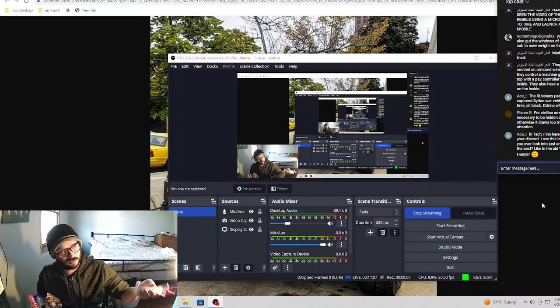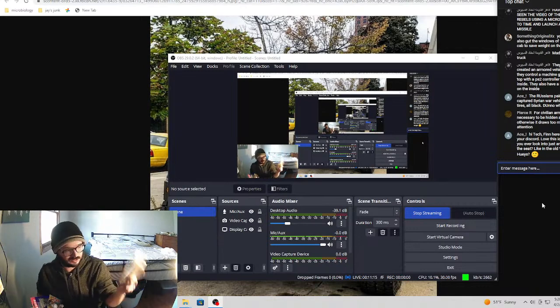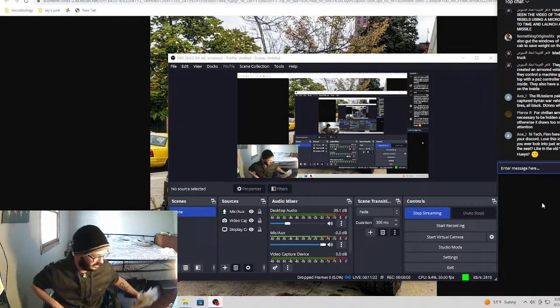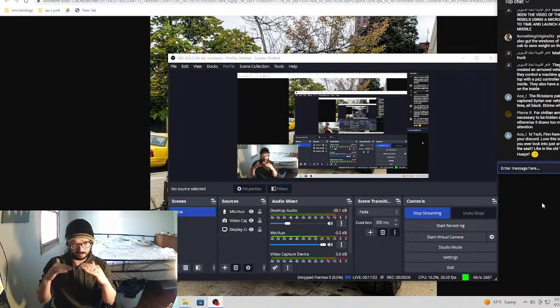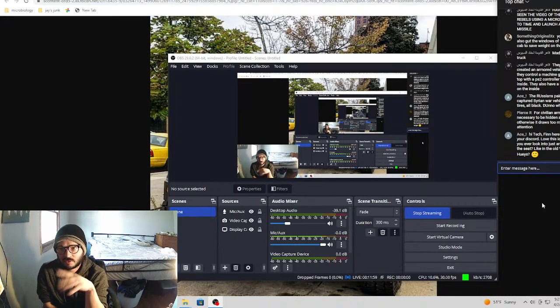That's one of them that I used for my acrylic two, three years back. This Gorilla Glue actually worked really well with glass, and it's very transparent. I just did some drop tests on it. I was very surprised at how well it kept the pieces from flying everywhere, just from doing weight drops on them. It just kept it all together. When you stack glass up, I've noticed that if you have a more elastic membrane in between the plies, it really does keep it from cracking. Because glass has a certain level of flex it can go before it breaks anyway. So having some elasticity between the layers of glass allows them to flex in on themselves without breaking, distributing energy and stuff.